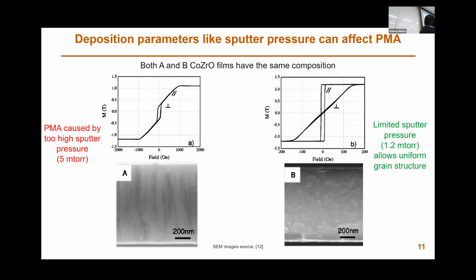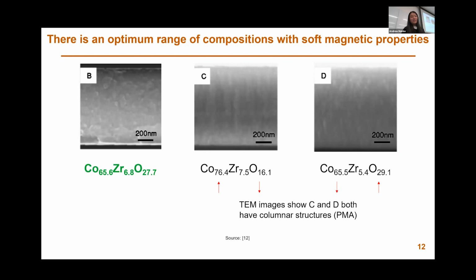And how did this happen? There are many factors that can cause a lot of PMA and these column-like structures. One way that this particular group found these structures is by increasing the sputter pressure. They found that if you use too high of a sputter pressure, you get these column-like structures, but if you keep the sputter pressure low, you get a nice uniform grain structure and happy loops. There's also a very narrow range of chemical compositions for cobalt zirconium oxide that have the properties we like. And that's typically around 60% cobalt, 10% zirconium, and 30% oxygen. If you're outside this range, again, you get these column-like structures and PMA. If you have too much oxygen, the oxygen starts oxidizing the cobalt and the entire material becomes more paramagnetic, which is also not what we want.